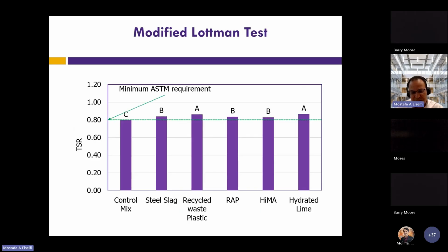Finally, the TSR, you can see that we set a threshold of 0.8 to be on the conservative side. So you can see that all the mixes met this 0.8, with the hydrated lime and the recycled waste plastic slightly better than the RAP and the HiMA and the steel slag. And again, the control mix was statistically grouped as the worst performer, as Group C.